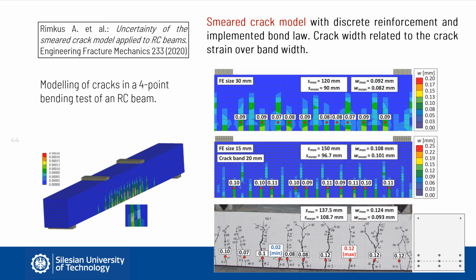The second example shows the use of a smeared model to analyze the width of cracks in a beam under 4-point bending. The width of the crack is derived from the cracking strain with the use of the crack band concept. The locations of the cracks are identified with a damage criterion. Cracks are formed when tensile capacity is reached, and in the finite elements in which cracking occurred, the softening behavior is described by the cracking strain. The results of the model are compared with the experimental tests to check the obtained crack spacing and crack width. Given the large amount of cracks whose location is not known prior to modeling, the use of the discrete model would be highly inefficient, while the smeared model allowed to obtain the desired results with less computational effort and still satisfactory compliance.